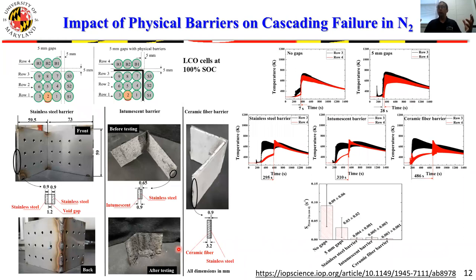by changing the geometry of the module. So one obvious solution would be to take cells apart. But when you do that, you of course reduce the energy density, and you are thus trying to engineer a battery module against its main constraint, which is a high energy density per unit volume. So we thought that one reasonable solution was to consider breaking the large module into smaller cell clusters and producing 5 millimeter gaps between the clusters, which is shown on the left-hand side, and potentially introducing some physical barrier between the cells.